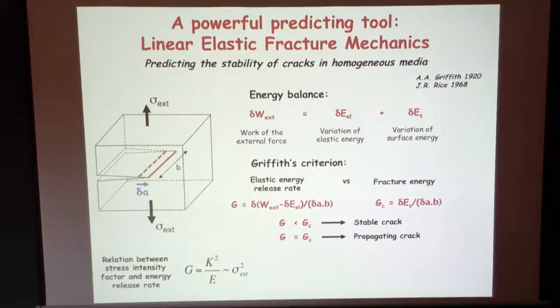Yeah, and it's really a good approximation that these plasticity and dissipative processes scale as the surface area of the... Not in ductile failure, for example. I think as long as you're looking at crack propagation over lengths much longer than the width of the region above or below that's involved in the non-elastic plastic deformation, then this works.